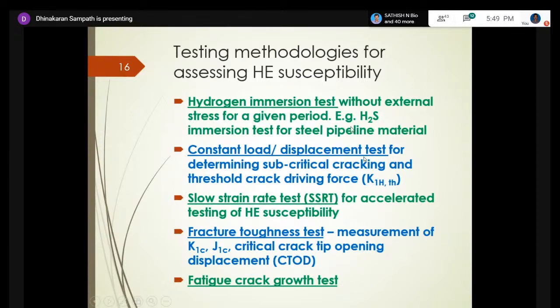In the case of some low alloy steels, such as pipeline material, they actually carry hydrogen sulfide. For this material, they take a piece of material and immerse it in the H2S solution without applying any external stress, and then understand if there is any crack. If the pipe is a seam pipe, that means it is made using welding, in that case they need a different strategy to expose both the body material and the weld, to see if just in the presence of H2S, due to hydrogen blistering, it forms any blister or crack.